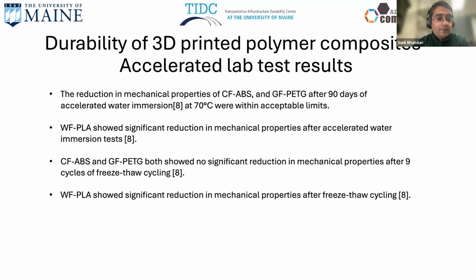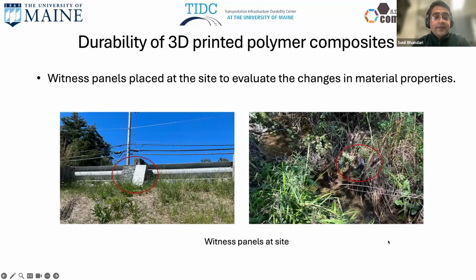Similarly, CF ABS and GFPETG worked very well and showed no significant reduction in mechanical properties after 9 cycles of freeze-thaw cycling. And again, WFPLA showed significant reduction in mechanical properties. We have also placed witness panels at site, which we plan to go back and retrieve and test in lab to see if they have reduced mechanical properties and by how much if they have. These are at site, and we plan to get them next year.